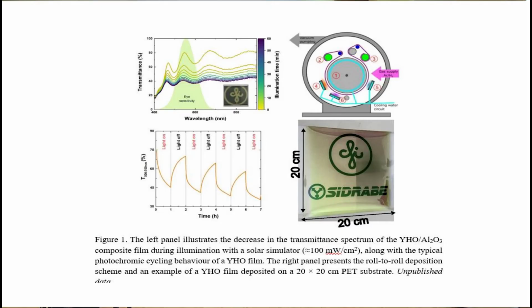You see also such a thin film tested in our institute last year, created in the group of Dr. Martin Zubkin. So it is a good contrast, about 30–40% during cycling. Obviously, the time is very sensitive to the deposition conditions, and we play with deposition conditions, with the pressure of hydrogen, argon and so on. As a result, we can obtain very good properties of such films. But still, we need to improve to have a more stable material.